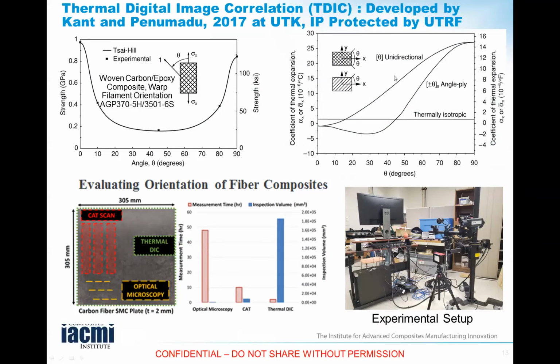So we utilize this information in our thermal DIC system we have developed here to derive spatially what the fiber orientation is. It is a cartoon that we are showing that if you do computed microtomography, it takes a lot of time for small volumes to get precise measurements. Optical imaging is even worse. So we had to develop another technique that's meaningful to complement these two, and that's our thermal DIC.